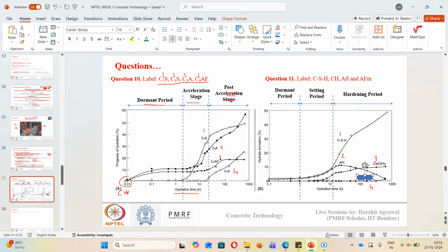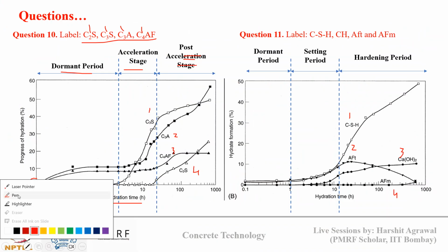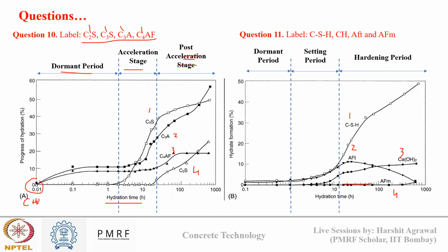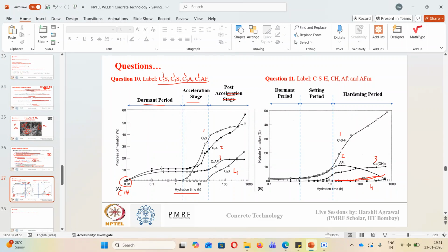And the fourth one will be AFM, monosulfate. As ettringite starts to decline, monosulfate will start to rise. So this curve should be like this. From here it should increase like this. Okay, are you clear with how the oxide compound composition changes over time, and how the final hydration products change over time?